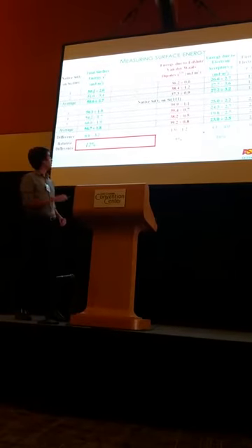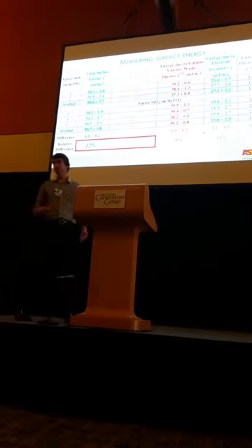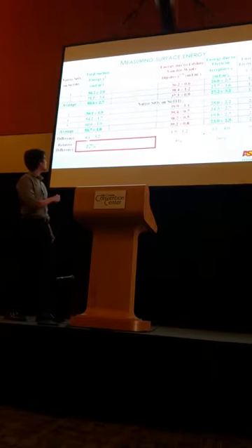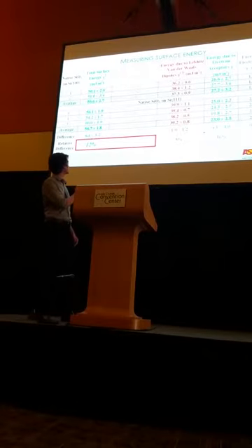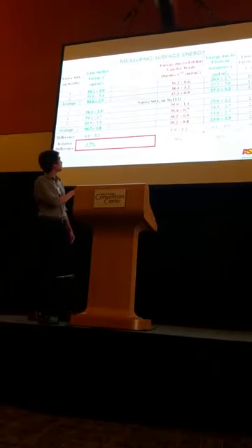So presented in this table is a collection of our calculated results. In this first column is our measured surface energy for our silicon wafers. We see that the average surface energy of silicon 100 is about 50.6 millijoules per meter squared, while the surface energy of our silicon 111 crystals is about 56.7 millijoules per meter squared. If we look at the relative difference between these, there is a difference in energy of about 12%. So the surface energy of silicon 111 is about 12% larger than that of silicon 100. This also matches up with our difference in surface density.